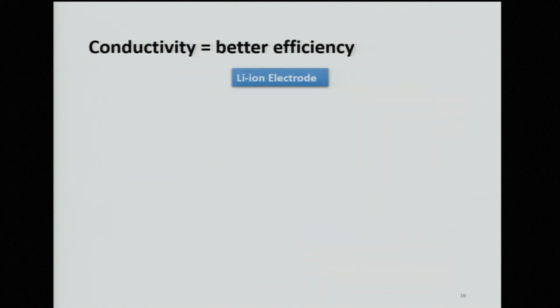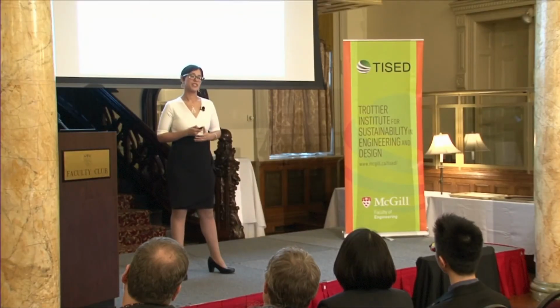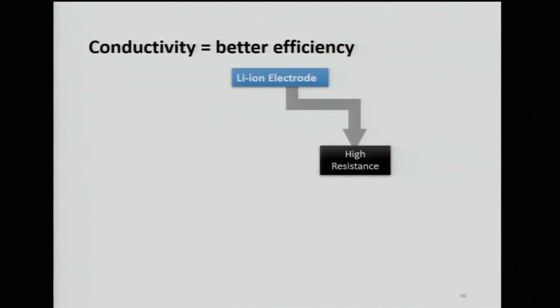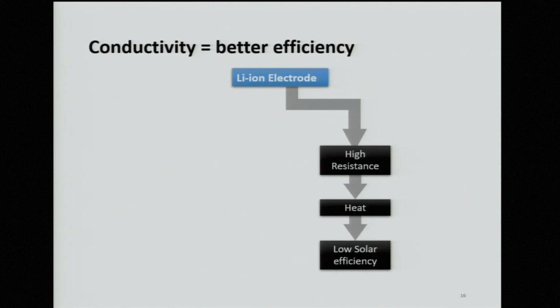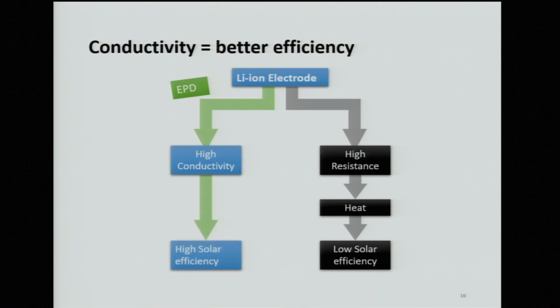Now, if you remember earlier, we were talking about combining lithium-ion batteries with solar cells. If we do this, then conductivity is a big deal, because low conductivity means high resistance. And when you have high resistance, you're losing energy as heat. And this means a low overall efficiency between your solar and your battery couple. But we don't have this problem with EPD electrodes. We have higher conductivity, so comparatively less energy is lost as heat. This means that our overall couple has a higher efficiency. So not only are we making lithium-ion batteries that perform great, they're greener, and now they have better efficiency.